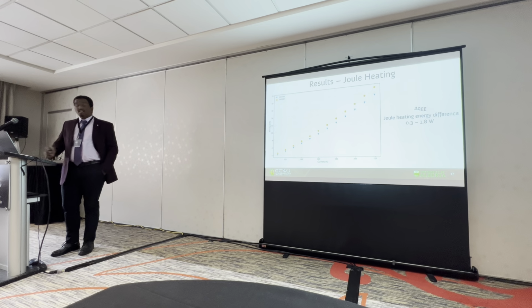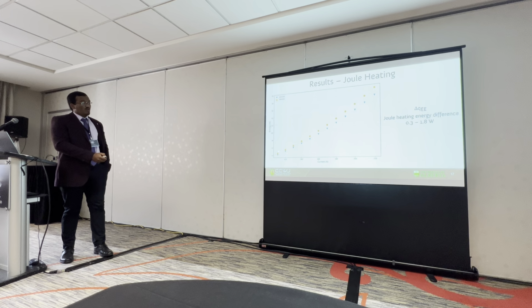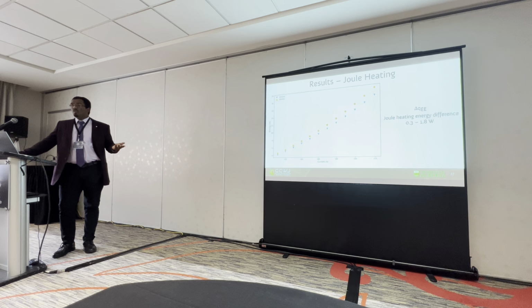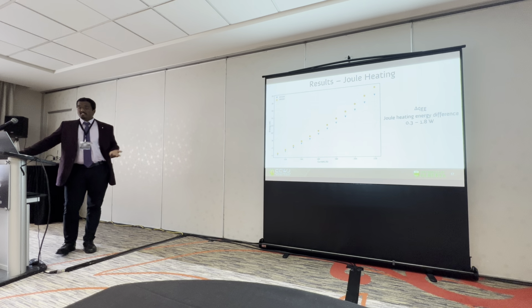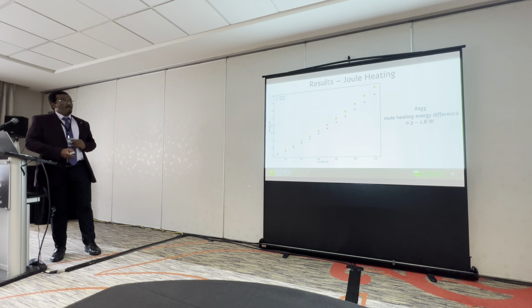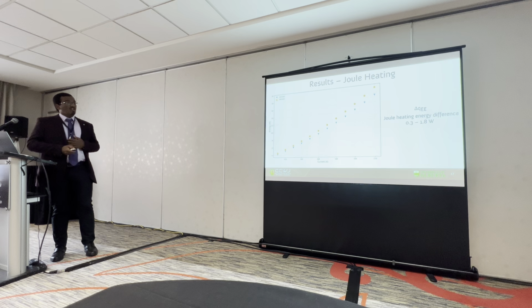So, the results of the Joule heating: 1100 is represented by the blue triangles, and 5183 by the orange circles. And this is as expected: the Joule heating value of 5183, which has higher electrical resistivity, is going to be higher. And that is true. It's higher across all the current ranges. But the point to note is that the difference between 1100 and 5183 is pretty small. It's approximately 0.3 watts in the initial stage and 1.8 watts in the final stage. This is the maximum difference in Joule heating generated for both alloys.